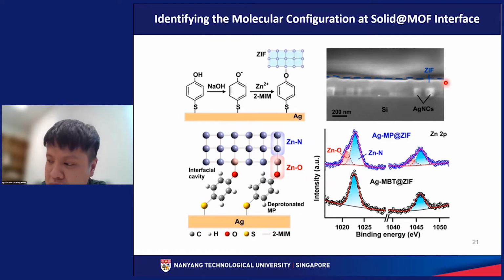But the main highlight of this slide is that right now for our design, we are assuming that the sulfur of our substrate is attached to silver through the silver-S bond, and on the other end, our oxygen atom from the phenoxide moiety is attached to the MOF layer through the zinc-oxygen bond. Okay, so this is our key hypothesis. Are we able to affirm this? So we affirm this using XPS or X-ray photoelectron spectroscopy. So from this example, we can see that there are two types of zinc chemical environment in our system. One is the zinc-oxygen. Okay. The other is zinc-nitrogen. So for our system over here, we are able to see two different kinds of zinc environment in our system.